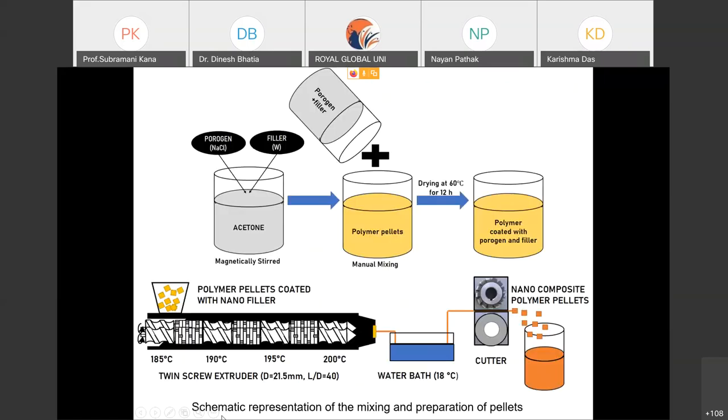And this one is how we are making the composite pellets. As I said earlier, this is a shape memory polymer, and the polymer does not have a radiopaque characteristic, so you need to add some radiopaque materials. Either you can use barium sulfate, which is well established and is used with PMMA for bone cement applications, or for diagnostic treatment in the stomach. It is already a well established biocompatible material, so either you can use barium sulfate or we can plan to use hydroxyapatite.